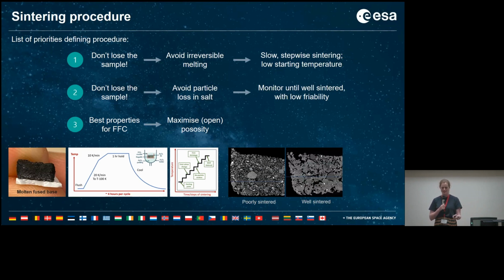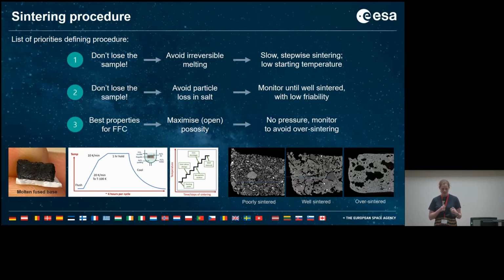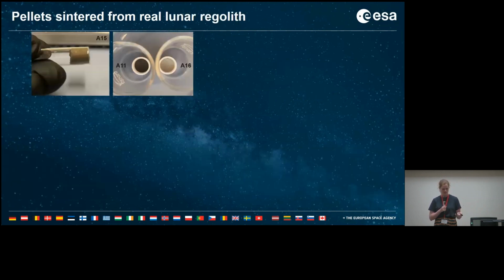It's worth saying that even though these are little bricks, they're terrible construction materials. They're extremely porous, and they're not bricks in that sense. They're trying to be as porous as possible. And so we didn't apply any pressure. We just had a loose powder bed and sintered that. And also we avoid over sintering and closing off the porosity by creating a glassy surface.